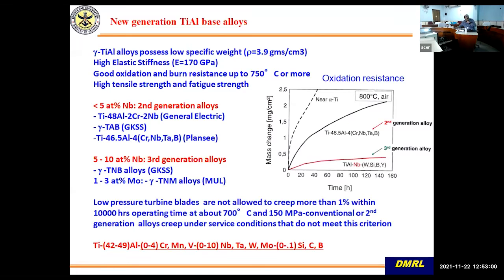Now, because you have added a lot of aluminium, the first thing that happens is it reduces the density. For gamma aluminide, the density is around 3.9, much lower as compared to normal titanium alloys, where the density is 4.5 grams per centimeter cube. So you have the weight advantage here, and the elastic stiffness also increases. It is around 170 GPa as compared to near alpha titanium alloys, which have got 120 to 130 GPa elastic modulus.